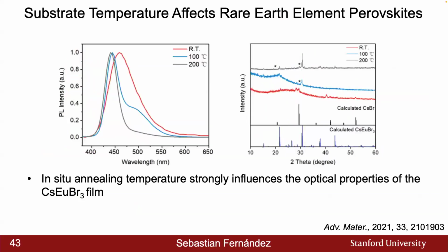Lastly, because we're limited in what we can do within the perovskite thermal evaporator, another knob is by looking at the in situ annealing temperature. So that is the temperature that we can apply on the substrates themselves as they're being evaporated on. And so the authors from the cesium europium bromide work showed that moving from a low room temperature to a higher 200 degrees Celsius temperature, when looking at the photoluminescence, we can see the decrease in the full width half maximum, which is important for the display application for these LED technologies.